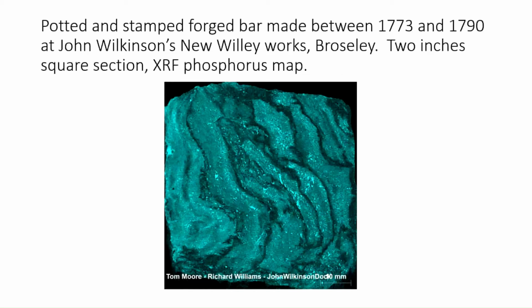This is a bit of serendipitous discovery. Somebody at the Ironbridge Museum had found some bars of iron in the Severn at Broseley. And so I put these on the XRF, produced the phosphorus map, and got this structure. Now, this is a solid piece of iron, but what's interesting about this, you can clearly see the bits of iron that were put in the crucibles and were welded together.